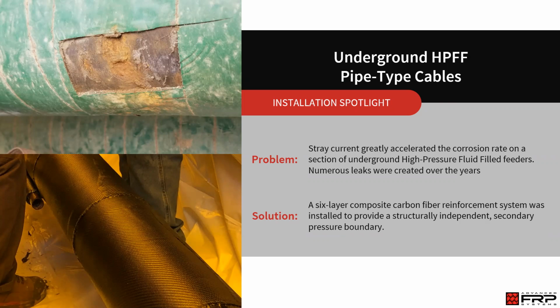We were able to fully reinforce this section of feeder, over 10,000 linear feet of pipe, with a 6-layer carbon fiber composite system. We showed that it was not affected by the stray current and that it would completely eliminate the corrosion of the host pipe, as well as providing a secondary pressure boundary.